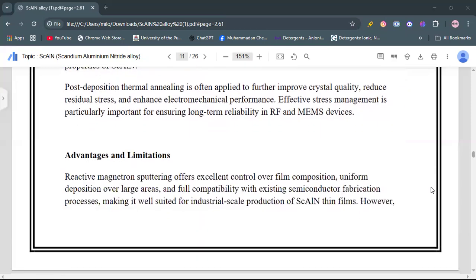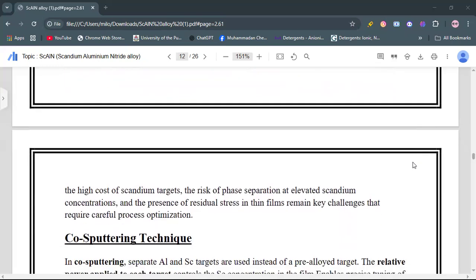Now, advantages and limitations. Although it is a very good technique to form scandium aluminum nitride thin films, it has certain advantages and limitations. First of all, let's talk about the advantages. It offers excellent control over thin film composition, uniform deposition over large areas, and full compatibility with existing semiconductor fabrication processes, making it well suited for industrial scale production of scandium aluminum nitride thin films. However, the high cost of scandium targets, the risk of phase separation at elevated scandium concentration, and the presence of residual stress in the thin films remain key challenges that require careful process optimization.